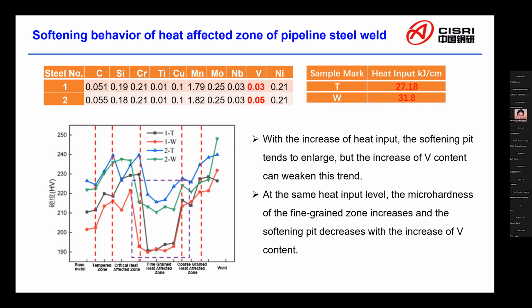At the same heat input level, the microhardness of the fine-grained zone increases and the softening width decreases with the increase of vanadium content. We speculate that the reason for this phenomenon is related to vanadium precipitating during the weld thermal cycle, or vanadium hindering the disappearance of dislocation substructure, but it still needs further experimental verification.